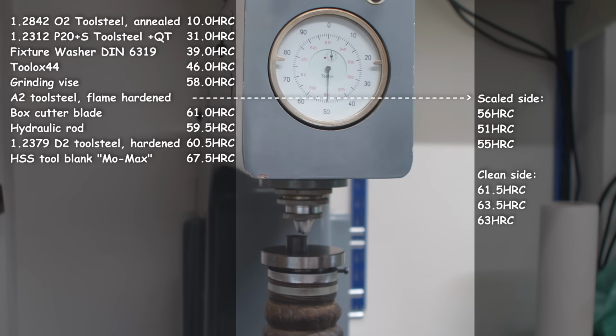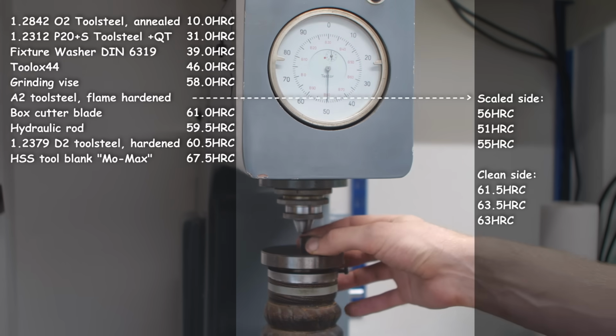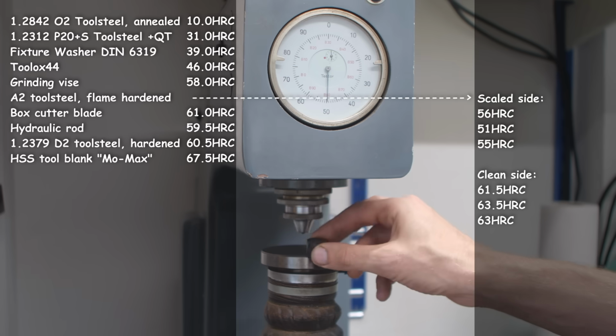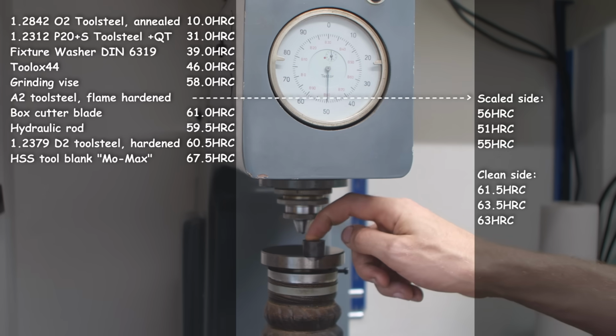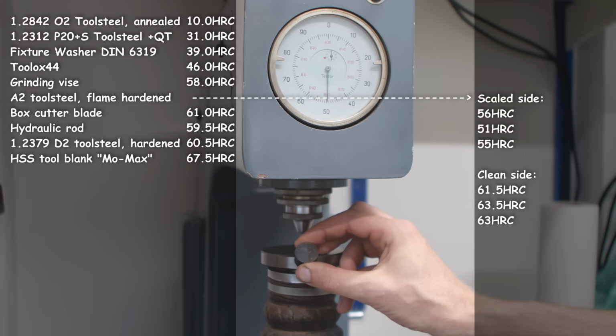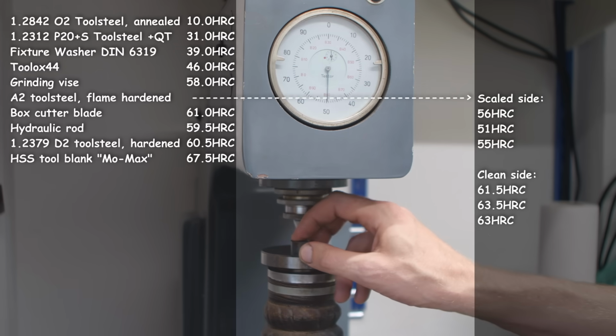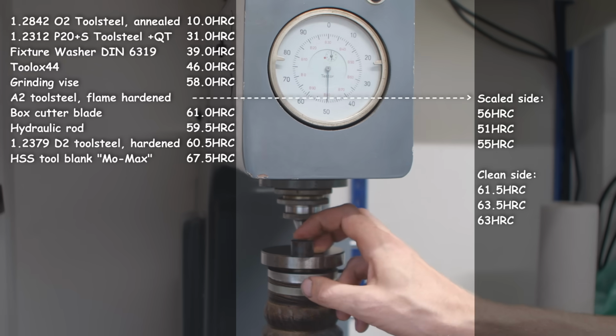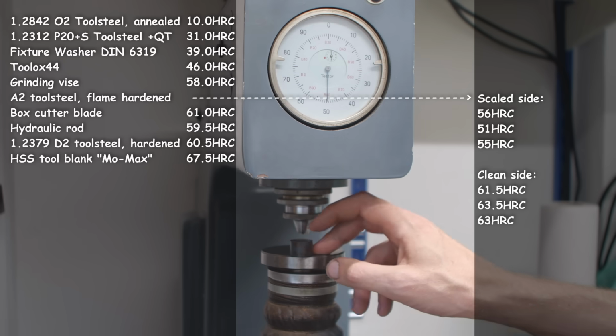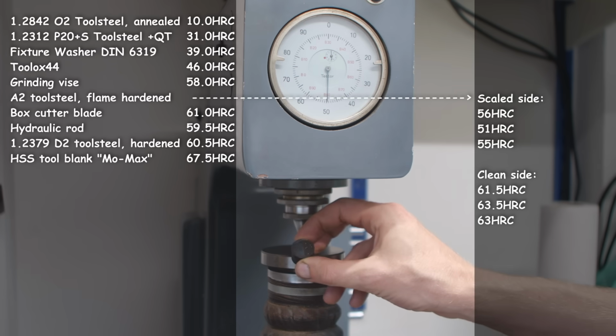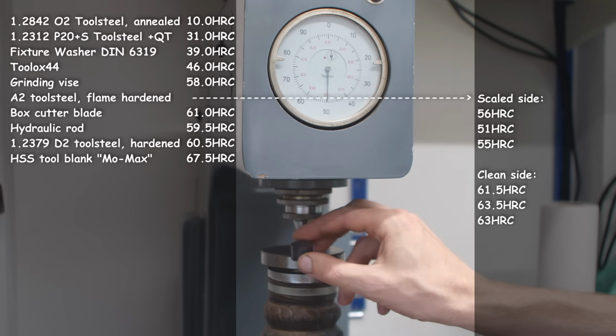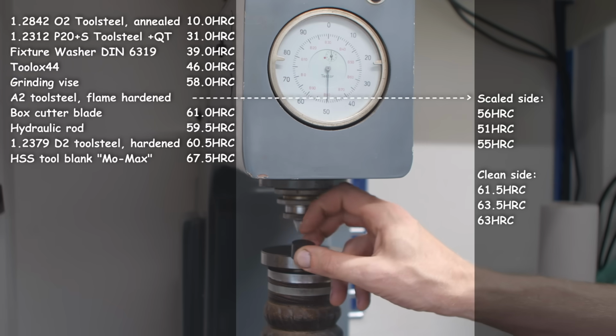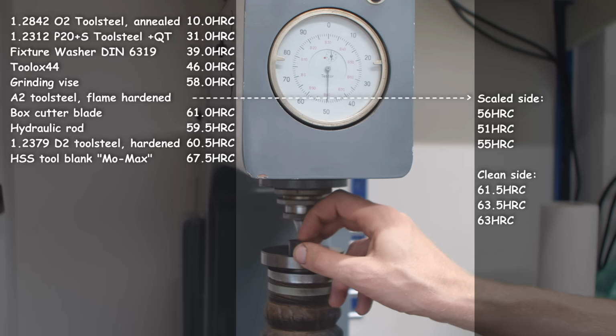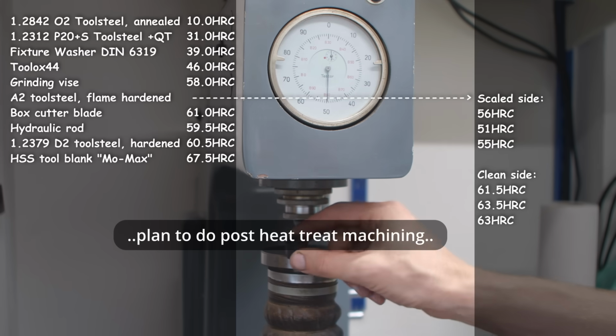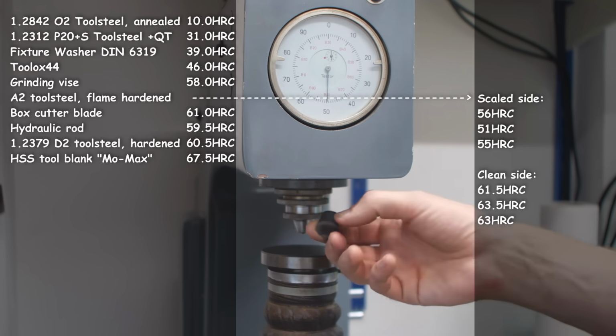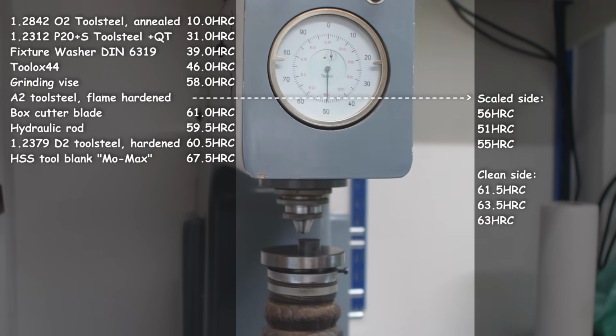So there is still some tolerance in my measurements because this is just flame heat treat. But the scale, well, there are two factors at play when you flame harden in an atmosphere. First of all, you have the scaling, which is this oxide layer that's kind of crusty, and also you are decarburizing the outer layer of the steel. So for real hardness, you want to get rid of at least the scaling and maybe even a few microns of the steel. If you do a flame harden, you plan to do a post heat treat anyways. Otherwise, you end up with not very nice parts.